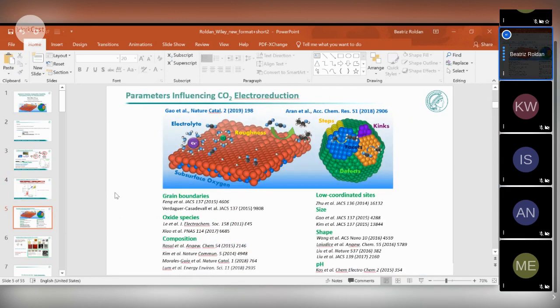First of all, there is a lot of literature already discussing beautifully many different parameters that affect the selectivity of CO2 electroreduction. For example, if you are working with surfaces or thin films, the roughness is very important. This has been shown to affect the activity. Also, if you have grain boundaries on these structures, if you have oxide species subsurface or at the surface of the catalyst, and of course the composition of your catalyst, and anything else that you have in the environment, the electrolyte is going to play a very important role. It could just serve to reconstruct the surface, for example. It could also provide an electronic effect,